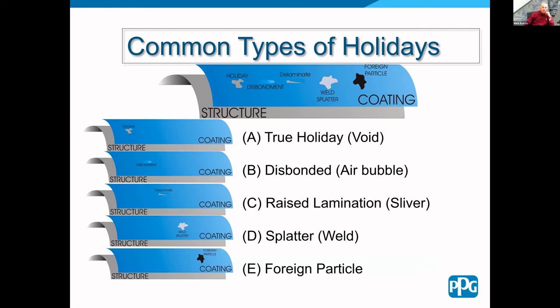So these are the common types of holidays. We have a true holiday, which is just a void. So we have an opening from the substrate through the coating to air, and it allows the electrical current to get back to ground when you're running a holiday detector over it. We have disbondment or an air bubble underneath. Most of the time, these are damaged to the point where we can get an arc to pass through that void. Then we have the raised lamination or a sliver. Something's under the coating. Raised lamination is a little bit different than disbondment. Weld splatter is always a headache, especially around joints on pipe or even on tanks where flange fittings come out. And then foreign particle, and it can be anything from blast media to just about anything that gets between the coating and the substrate.